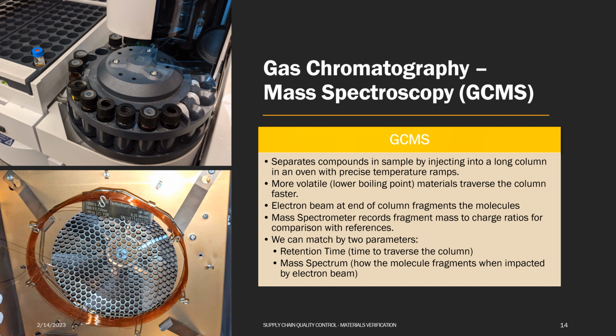The last technique that I used to look at this material was gas chromatography with mass spectroscopy, GCMS. GCMS typically requires dissolving the material in a liquid. In this case, it was isopropanol. The sample gets injected into, in this case, a 30-meter long column in a temperature-controlled oven. Volatile molecules make their way through the column more quickly. Bigger molecules with higher boiling points take longer to get through the column. So we're separating things and identifying them as they come out with the mass spectrometer.